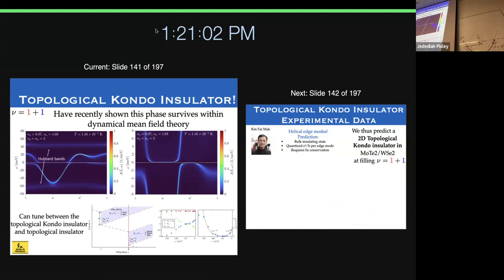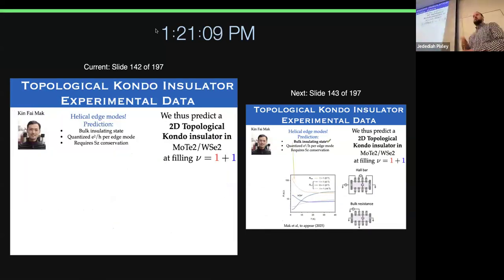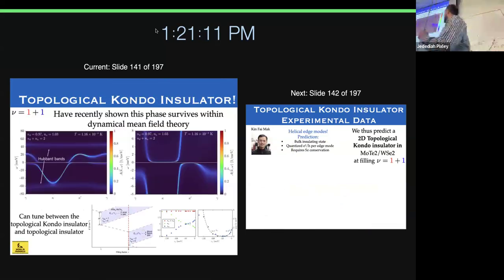So this is something we're after right now within dynamical mean field theory. But let me now show you some really exciting data that's not out. So that transition should be continuous. So as far as I understand, the topological Kondo insulator, topological insulator is a crossover. And then you go to a trivial insulator. Yeah. So there's a transition here, but there's a very non-trivial crossover between a topological Kondo insulator and a topological insulator that nobody's really studied at all. So my impression always was that these were sort of adiabatically connected phases. Like, how do you really sharply define topological Kondo insulator here?